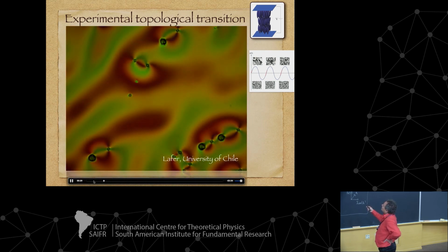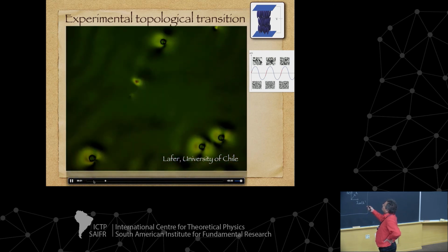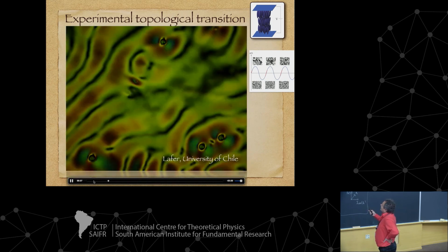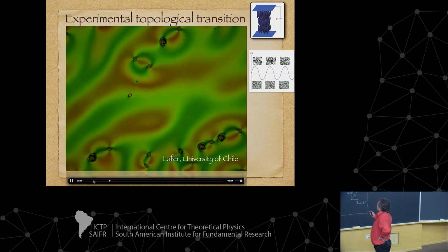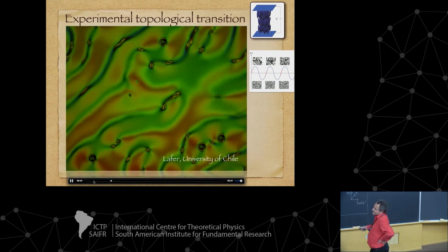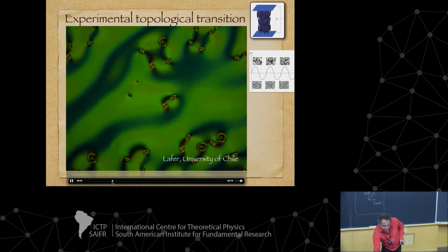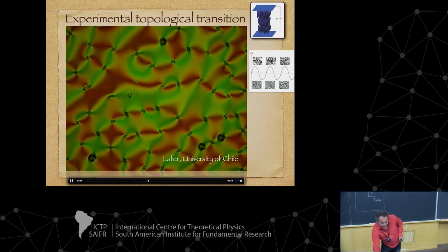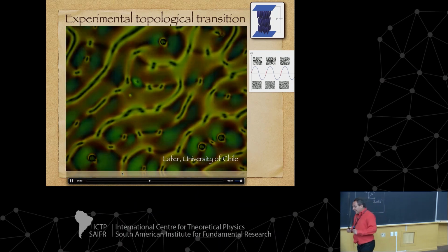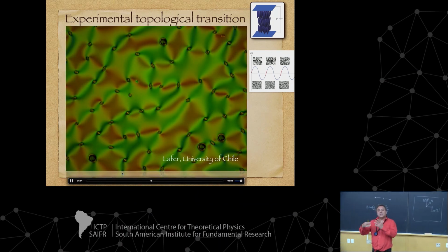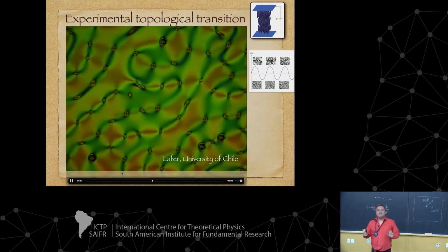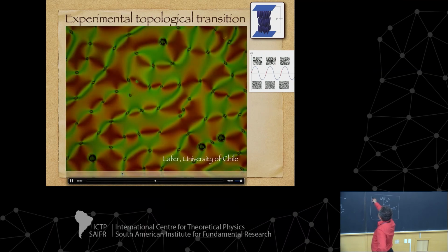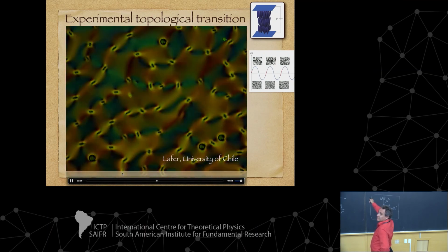This is also a sort of topological defect. It's possible to show that this is a sort of skyrmion. But the important thing is that this induces vortices, so you have one positive, one negative, another. So the imperfection induces vortices, but the unexpected thing is if you wait and wait and wait, the number of vortices increases. And the vortices, compared to the initial theory I showed you, appear in very well-defined positions. Look, this appears here, after a period appears close, after a period appears close.